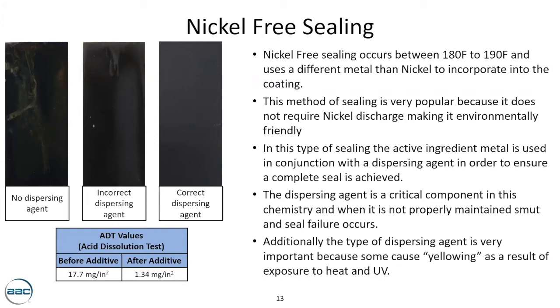So what this slide shows is basically three different panels. One, no dispersing agent. The second one, the incorrect dispersing agent. And the final one, the correct dispersing agent. And much like the hot nickel and the mid-temp nickel, these dispersing agents break down over time. So it's very important that we find which one works the best.